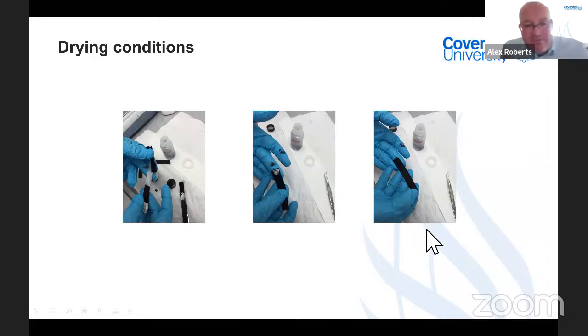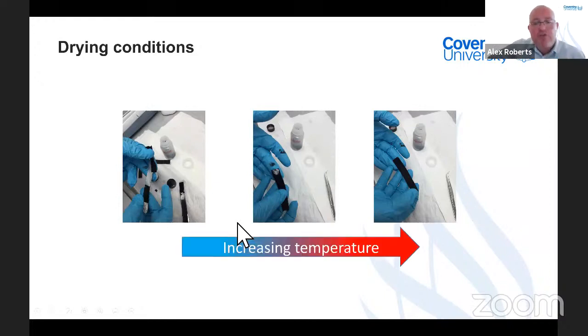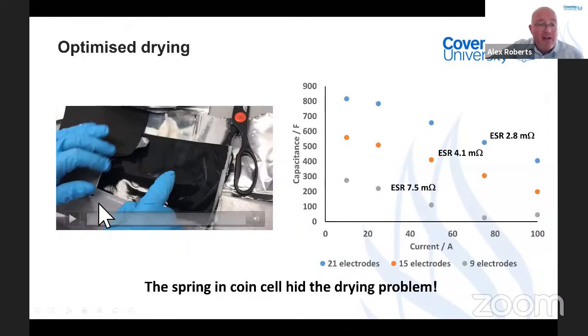So after looking at the various parts here, I thought this could be due to the drying. What you can see here is I've changed the drying conditions in the reel-to-reel coating and then immersed a flag of the electrode into some electrolyte and checked the adhesion. As you can see, for this particular system, as I increased the drying temperature, I got better and better adhesion. So after I'd worked all of this out, it was time to see if we were correct. And you can see here, this is a cell that was cycled, and we can see the adhesion before I'd open the cell up and everything would come off.